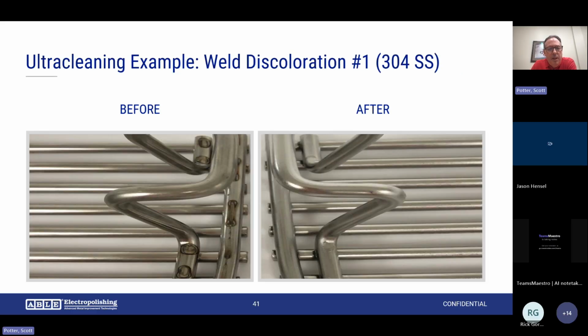Here's an example. It's a weldment. It's a food rack of some sort or shelf. You can see the weld discoloration from the resistance welding on the left there, and you can see how the electropolishing cleaned up that discoloration. As I mentioned, you clean up that carbide precipitation situation and leave the part very passive, clean, and it improves the cleanability as well. Things don't like to stick to it.